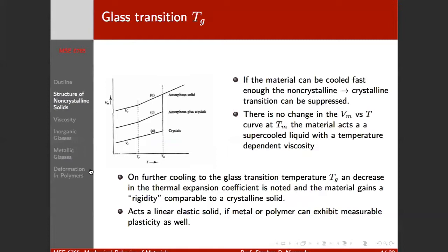And if we keep cooling, we reach what we would call a glass transition state, where our material gains a rigidity or a stiffness, and no longer behaves like a liquid, and we compare it to a crystalline solid. So even right off the bat, we're talking in fairly loose terms. We can define the glass transition a little more rigorously because in most cases we see a